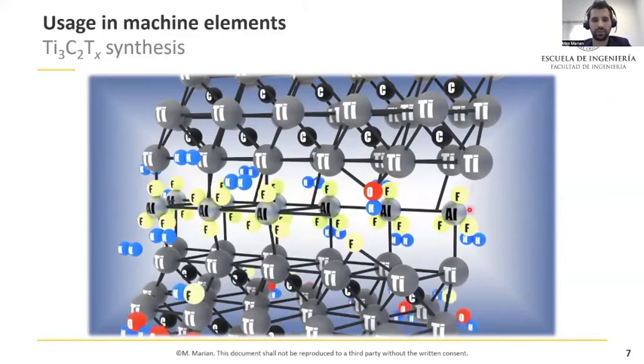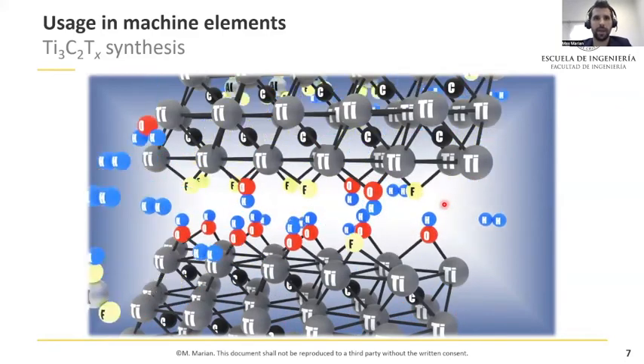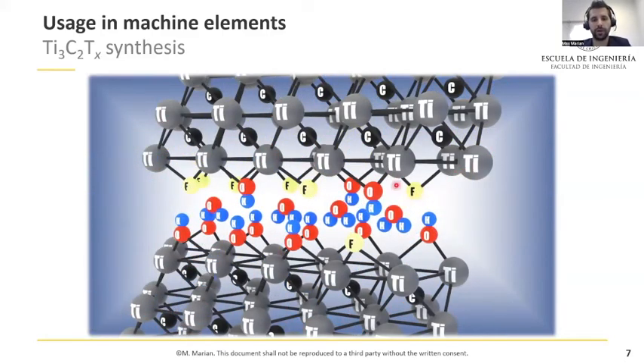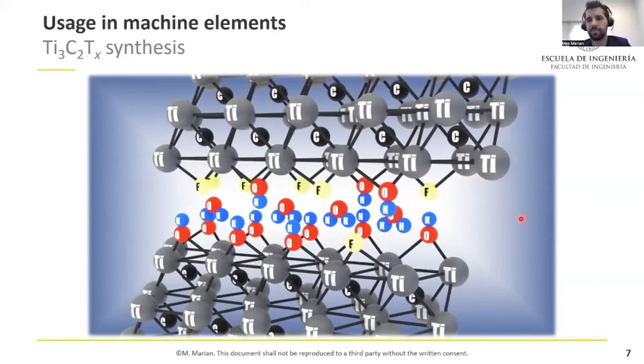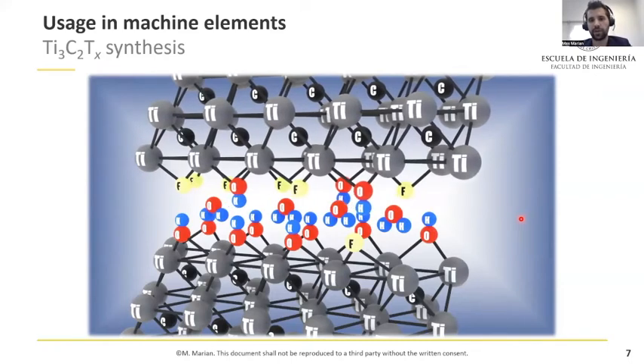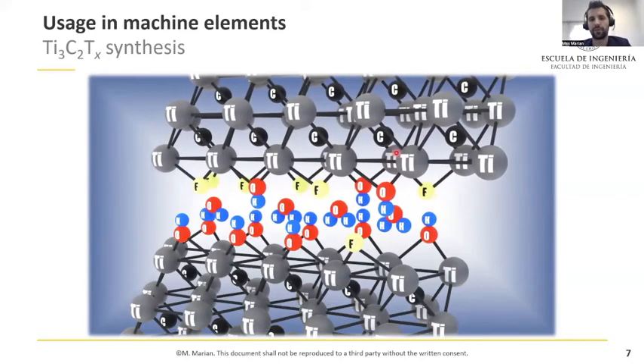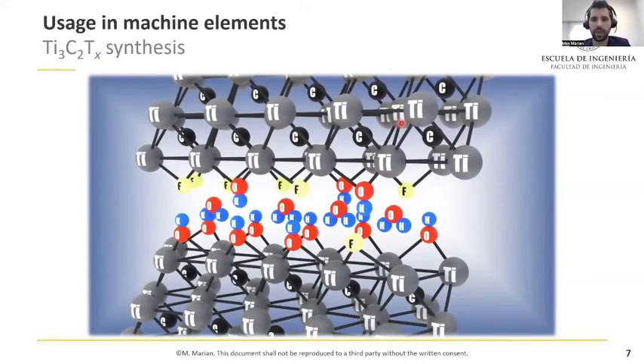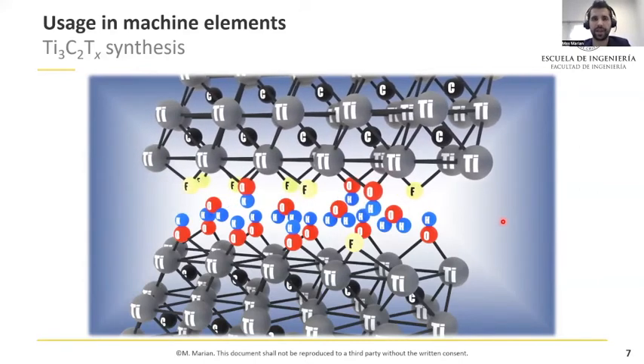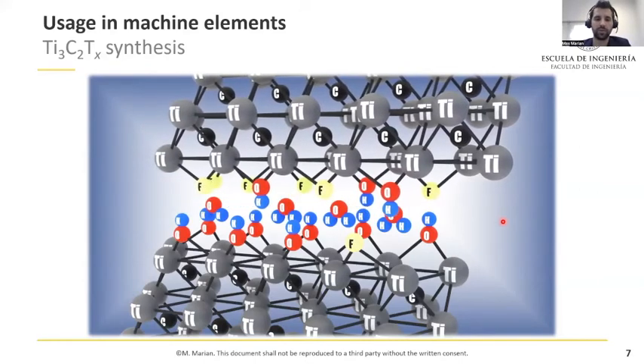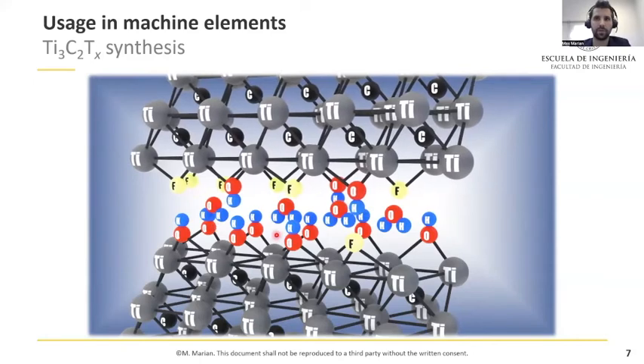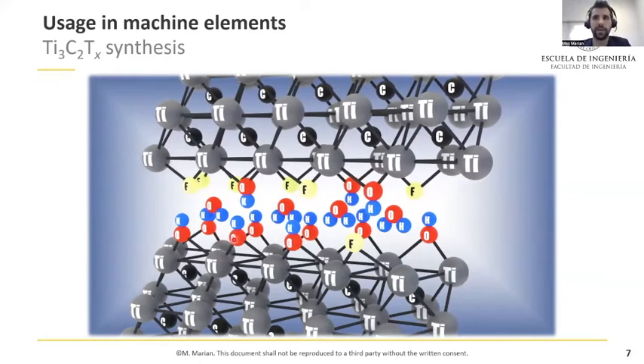we can selectively etch the aluminium layer out of the MAX phase, leaving only the M and the X, hence the name MXenes. In our case, this would be, for example, Ti3C2. Due to the selective etching, we also get so-called surface terminations, which are formed by the elements from the acid, the water or the air at the free ends of the sheet.